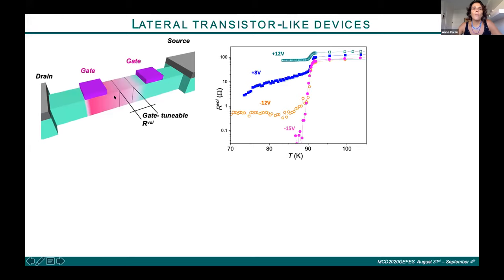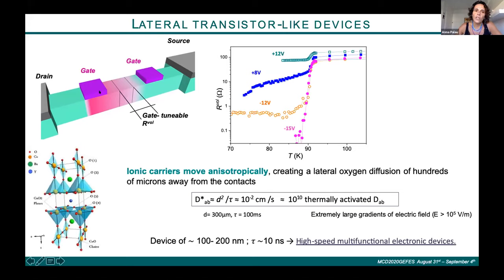Yes, okay, thank you. We can also evaluate the TC at different places of the bridge. For example, here we can go from this non-superconducting state to the superconducting state, recovering completely the TC by applying voltage pulses in this lateral way. And we can evaluate the velocity of the oxygen going from one gate to the other by considering the distance between the two gates and the voltage pulse that we applied, which is not very fast, so it gives us a lower value of the diffusion of these oxygen atoms. And we obtain a diffusion which is very, very fast, 10 to the 10 times faster than what is usually reported for thermally activated diffusion of oxygens along the ab planes, which gives us the opportunity to design systems with high speed due to the extremely large gradients of the electric field generated in the material.